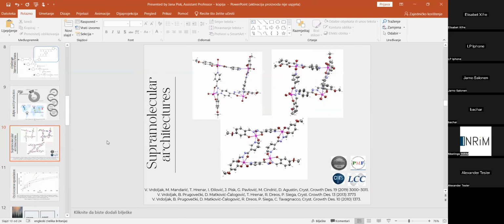And of course, the synthesis of this kind of complexes is not the simplest one, but it is possible to achieve complexes that have supramolecular motifs. And in fact, they have this kind of holes. Here are presented 3 different tetranuclear molybdenum complexes, and the 2 upper complexes show more or less similar structure, similar geometry, while the complex below has a somewhat different structure.